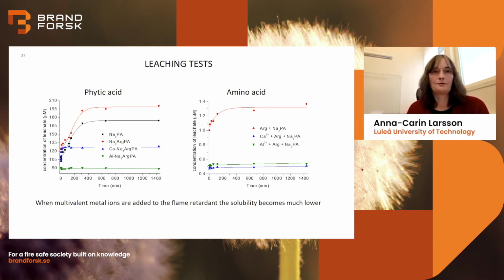So then our final part, to see the solubility. We did some leaching tests. We took a piece of our cotton treated with flame retardant, put it in water, and then at regular intervals, we took out a sample of this water to see how much of the flame retardant has dissolved into the water. So the upper curve there, the red and the black one, shows when we have our soluble flame retardants.